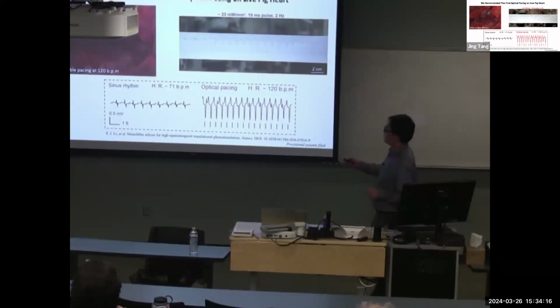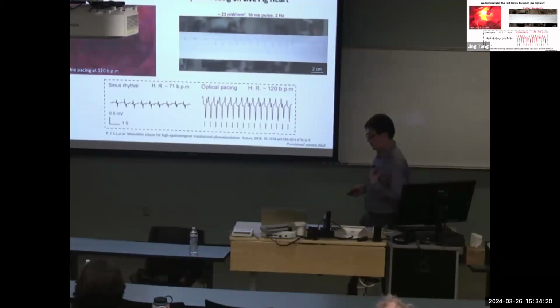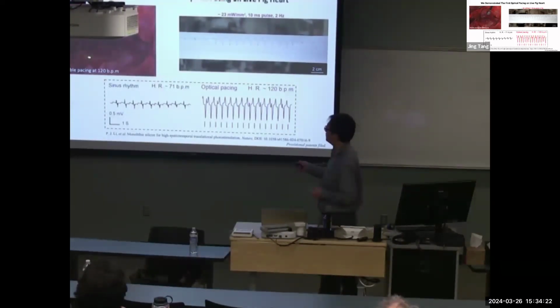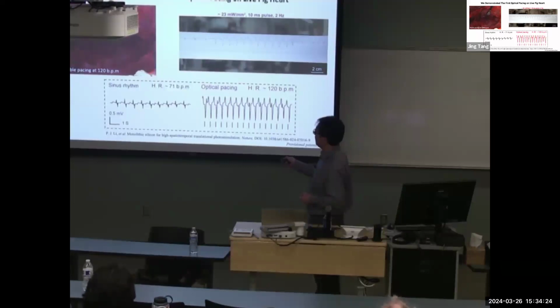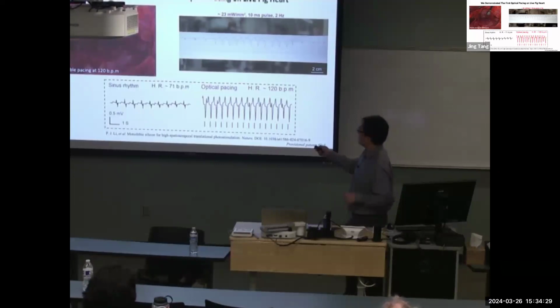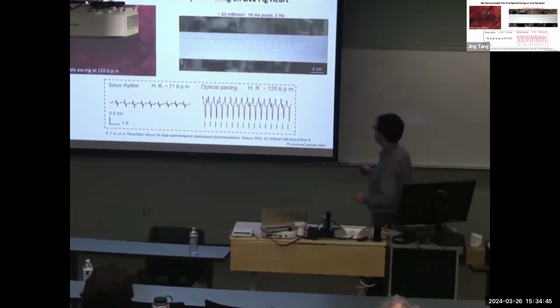This is the open chest surgery. This is the pig heart. The pig heart is even bigger than the human heart. The pig is more than 200 pounds. On the surface, there is a piece of silicon membrane. It's a monolithic membrane without islands, without pixels. And this is the optical fiber. This is just a very simple experiment showing that overdrive optical pacing in a larger animal is possible. Here it shows the data trace before and after. You can see an increase of the beating rate up to 2 hertz.